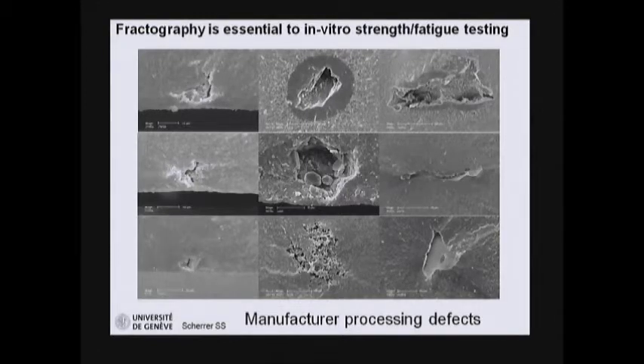You do your strength testing. If you don't look under the microscope what's going on, you will not be able to interpret why your Weibull modulus is low or why you only have a 700 megapascal strength instead of a 1000. Well, unfortunately, these are processing problems, pores from which the failure started in bend bars, sintering defects, processing defects, alumina inside zirconia. This is MgO, CaO, calcium oxide.